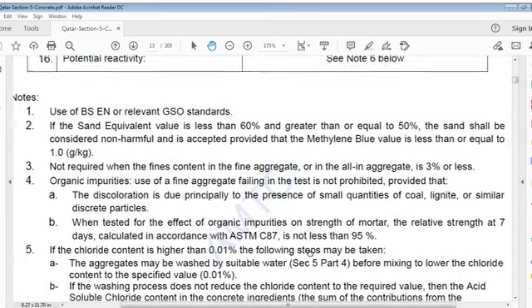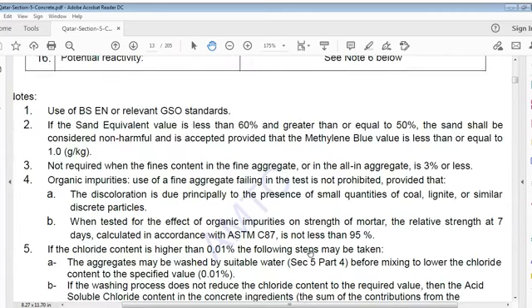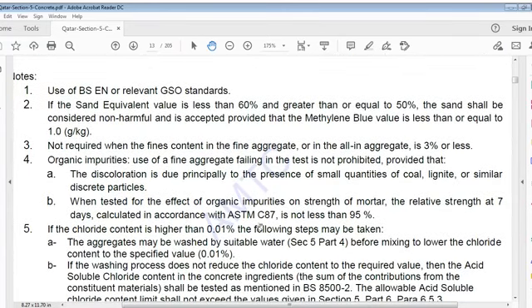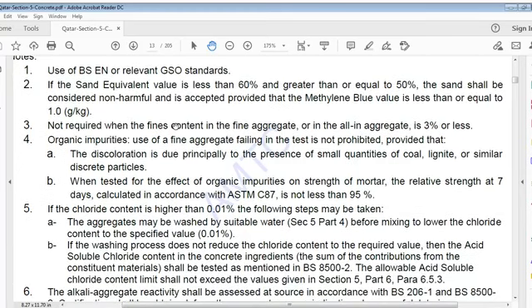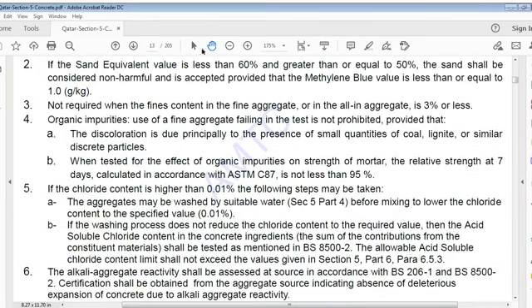Now it says notes there. Use of BSEN or relevant GSO standards. This GSO stands for Gulf Standard Organization. If sand equivalent value is less than 60% and greater than or equal to 50%, sand shall be considered non-harmful and is accepted provided that methylene blue value is less than or equal to 1 gram per kilogram. Not required when fines content in fine aggregate or in all-in aggregate is 3% or less.